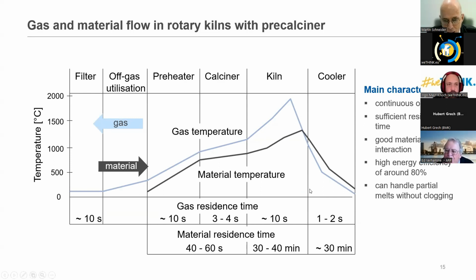The reason is that we have a countercurrent system here. If you go from left to right, you go from the quarry, the material is fed to the kiln, and here you have the clinker. The material is then entering the kiln. It's heated up in the counterflow of the hot gases from the combustion. It's going up here to almost 1900 degree gas, 1400 degrees material temperature.